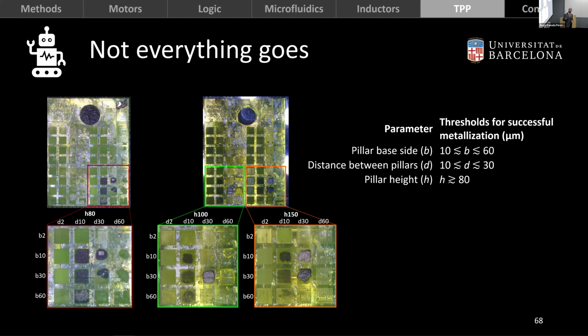And after doing that, we saw that not everything goes. So some patterns do catalyze metallization and some don't. So from this, we were able to find approximate thresholds for those parameters for where the metallization is successful and where it isn't.